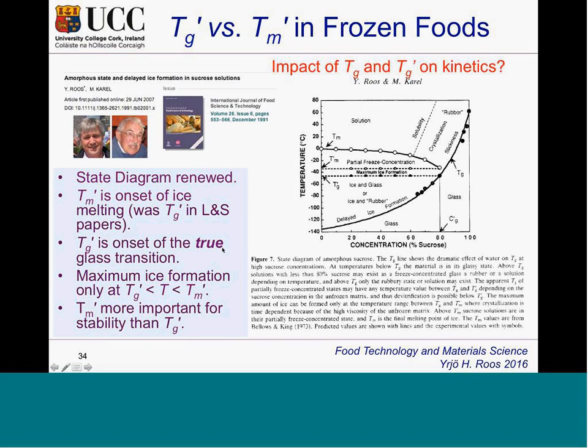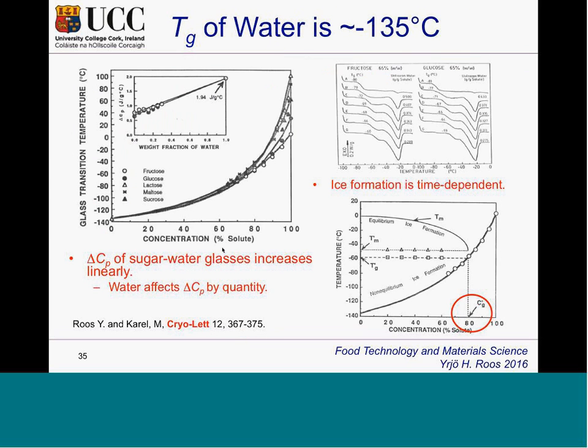The problem is that these two transitions are overlapping, and you may not be able to identify where exactly is Tm prime, but neither can you see the whole glass transition. There, the glass transition starts, has its onset, and is immediately followed by the Tm prime. We also have a number of measurements to show that the temperature of ice formation is very time dependent. Whether fructose or glucose or sucrose, in a solution where there's some water that can freeze, but not too much, we can see that the longer we allow freezing to happen, the higher the glass transition, and then we can approach a maximally freeze concentrated state.